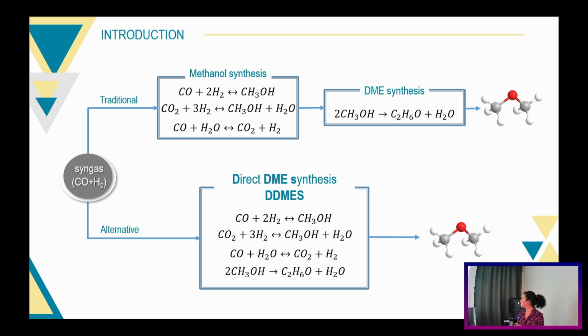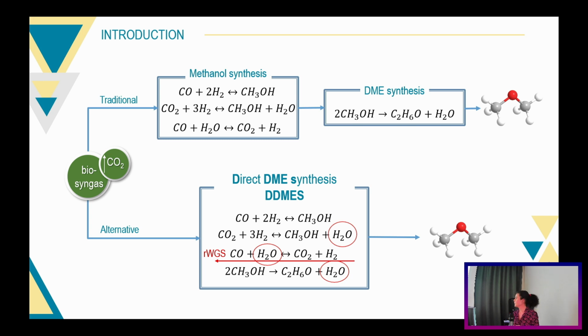One of the main challenges for the development of this process is that there is a lot of water inside the reactor, and this effect intensifies when we start from a biomass-derived syngas because its content in CO2 is much higher. This makes the reaction happen backwards, which is the reverse water gas shift reaction, producing an extra amount of water. This water is detrimental for the typical materials in the catalytic beds used for the study of this process.